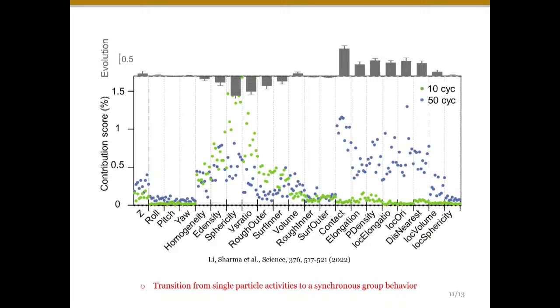But as the electrode moves towards higher cycles, like after 50 cycles, the blue parameters provide much more contribution, which is more of a group behavior nearby, like how much is the distance to nearest neighbor, how much is the packing density, and those kinds of things.